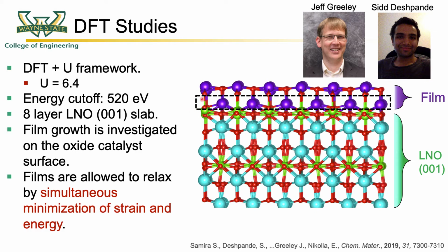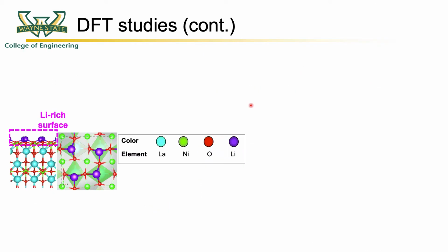The novelty of these calculations is the fact that a film of LiO2 and Li2O2 is simultaneously minimized in energy and strain as compared to the absorption of a single molecule of LiO2 or Li2O2 to describe the catalytic performance. It is initially observed that the near-surface lithium-rich region occupies a threefold oxygen site on the surface of the electrode.